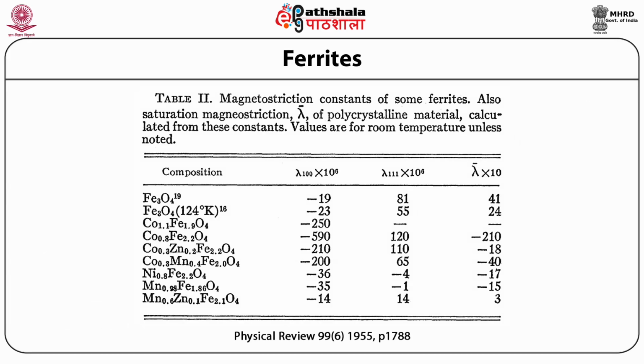The following table shows the magnetostriction constants of some ferrites. It also shows the saturation magnetostriction, that is lambda bar, for polycrystalline materials, which is calculated from these constants. Note that these values are for room temperature. So, for all the compositions, we have a specific lambda, or we can say the magnetostrictive coefficient, which is positive for some materials and negative for the other materials.